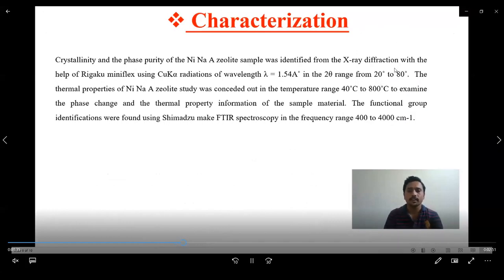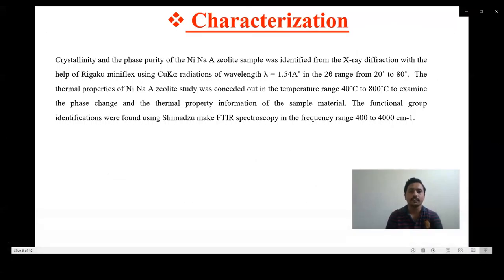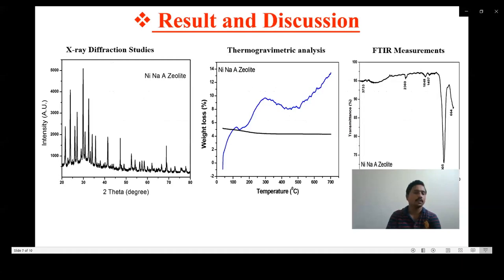For characterization, the film is characterized by XRD with a wavelength lambda of 1.54 angstrom and up to 80 degrees two theta value. TG-DTA is done from 40 degrees Celsius to 800 degrees Celsius to find the different phases and thermal properties. And for FTIR, the scanning range is 400 to 4000 centimeter inverse.